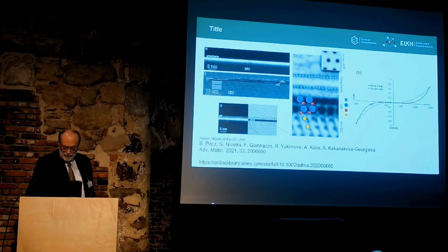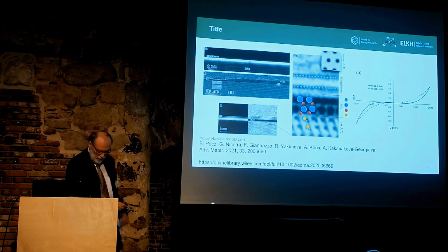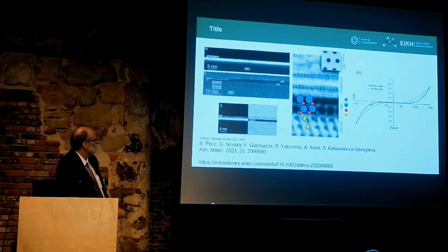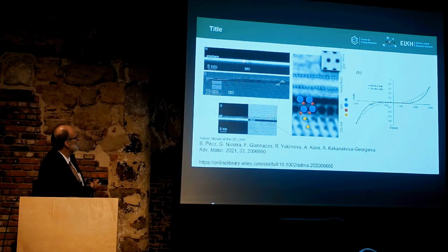And we had some success, and in the last couple of years, I studied two-dimensional semiconductors, including two-dimensional nitrides. We tried to synthesize indium nitride, aluminium nitride, and gallium nitride in a very thin layer between graphene and silicon carbide. First the epitaxial graphene was formed on the silicon carbide, and then in a CVD, chemical vapor deposition process, indium was intercalated here, and we managed to cover 90% of the surface with a bilayer, and the remaining part was a little bit thicker.